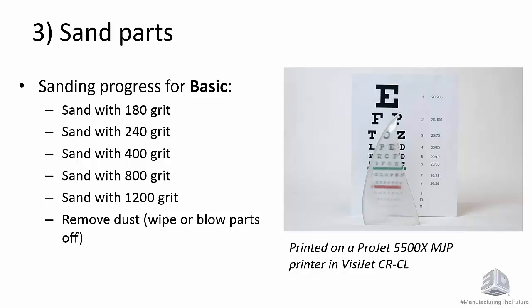So the sanding process for basic is you start with 180 grit, then you go to 240, and then when the sanding lines are gone from 180, then you go to 400, and then you go to 800, and you go to 1200. Sorry, I couldn't really think of a great way of expressing this, but basically you have to progress from rough sandpaper to smooth sandpaper, and you can't go too quickly, otherwise you won't get rid of the sanding lines from the previous sandpaper. And then at the very end, you want to remove the dust, either by wiping or blowing off parts.